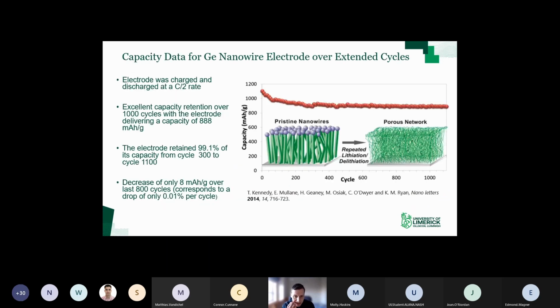So when we charged and discharged these, we found that they had an excellent capacity retention. So we were able to get well over 1,000 cycles with minimal capacity fade, I would say. There was a capacity fade initially, but it stabilized after more or less, you can see a slope change here, after about 100 cycles. And beyond that then was very stable. So we were obviously very happy with this. From 300 cycles on, you can see the electrode retained about 99.1% of its capacity, which, as I said, we were very, very happy with.